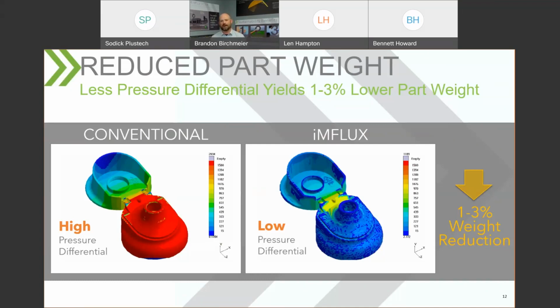Also, that 1 to 3% weight is typically happening while you're trying to achieve your gate seal. When you're transferring your process and you're using hold time and hold pressure, you're actually moving a little bit of material as you're waiting for that gate to freeze off. That weight is usually about 1 to 3% that we're not putting in because we don't need the excess time to achieve gate seal. Again, you're going from a very high speed process to a pack and hold phase. You have a much larger gate orifice to seal off versus the iMFLUX process where we're using very low shear and very low velocity at the end of our process where gate seal is almost immediate.